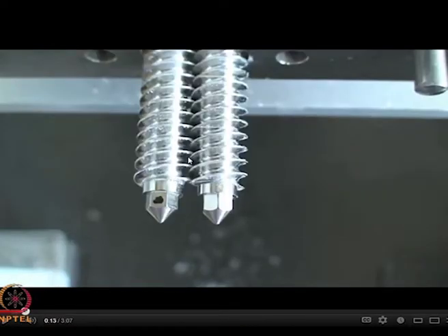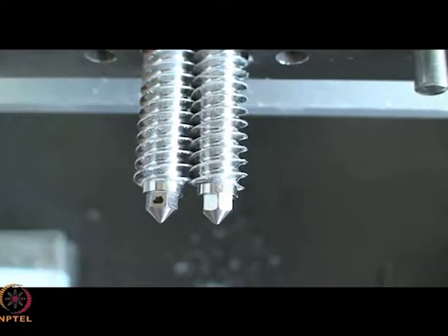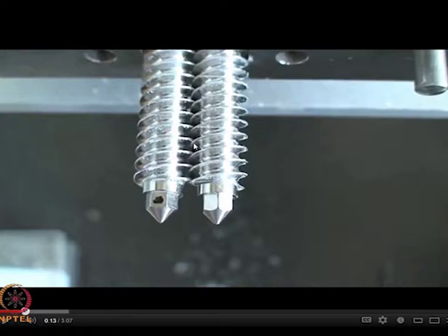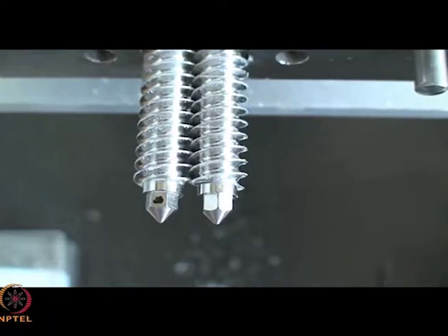When we are mixing with ceramics, what happens is that the polymer chains have to be really torn so that the ceramic powders do get wet by the motion of the screws. If you look at this screw, look at the spacings. This spacing is very important for polymer extrusion, and if we have a hard ceramic powder, you should understand how carefully these screws must be placed, especially because they will be working in a counterclockwise direction.